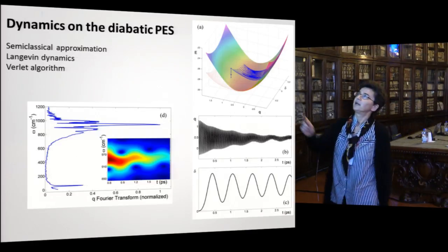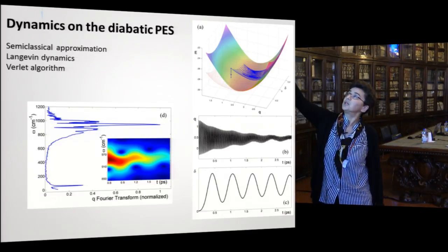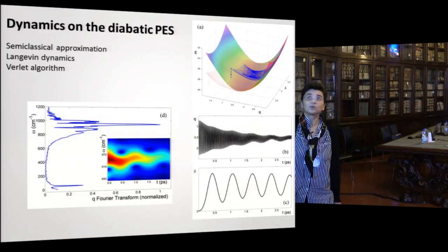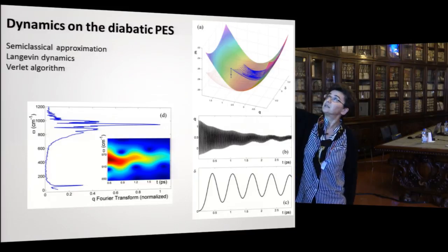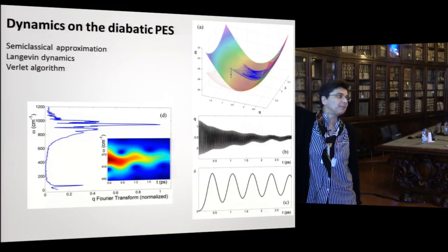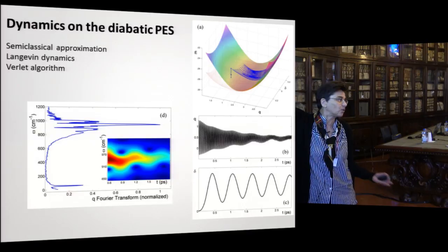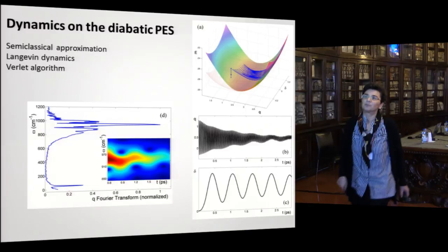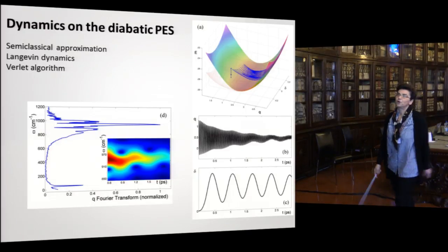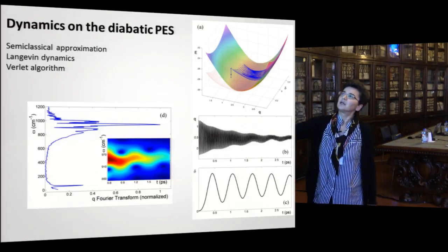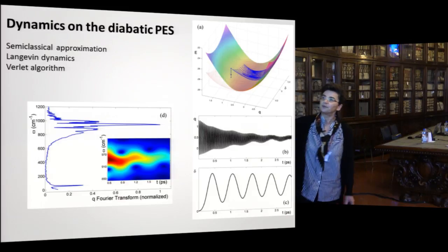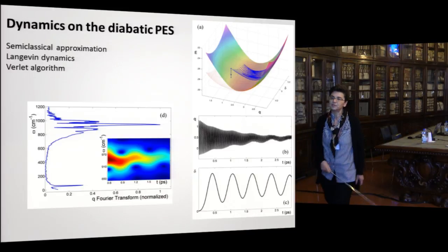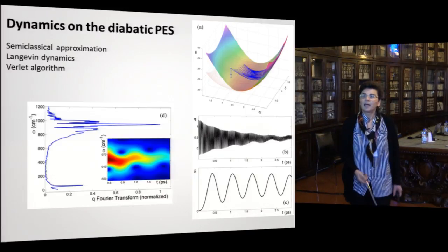And we have, this is not very easy to see. This is the ground state. This is the diabatic potential energy surface. So our model is that we excite on the diabatic potential energy surface that here coincides with the adiabatic one, but then the motion goes on the diabatic potential energy surface. And of course, the dynamics is now very easy, and you have Q oscillation at high frequency. Q is the molecular vibration, delta oscillations at low frequency, and you can Fourier transform.